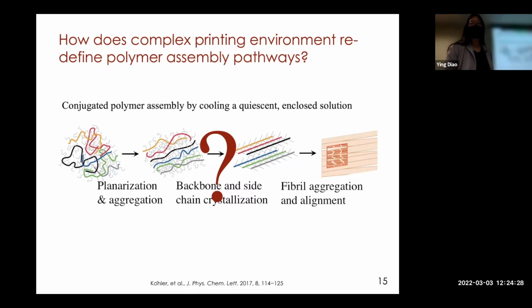So we hypothesized that during printing, the assembly pathway is drastically different from what is known. This is a pathway that was figured out a few years ago. If you put a polymer in a vial and cool it down to assemble, the polymers will first planarize at lower temperature, and then they will aggregate, and different parts of the polymer may crystallize separately. For example, the backbone and side chain can crystallize in separate steps. That forms nanofibers, and the nanofibers can assemble in a colloidal fashion.